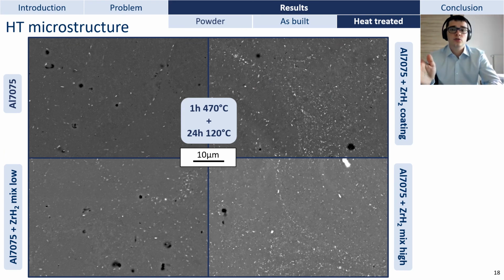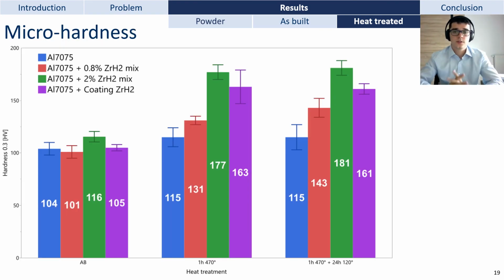Now let's look at the microstructure after the complete T6 heat treatment. We can see that there is not much change compared to the solution heat treatment. So let's now link this microstructure with some microhardness results. This final graph compares the microhardness of the 4 alloys in the as-built condition with the hardness after the 2 heat treatments I've just introduced.